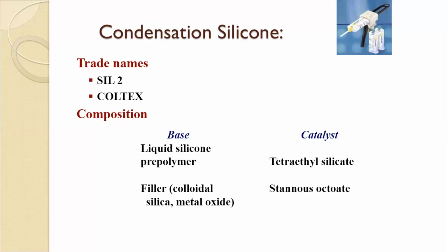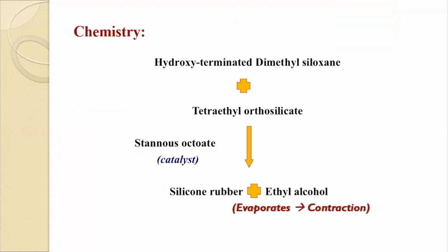Your base paste would consist of alpha hydroxy terminated polydimethyl siloxane. The curing of this material involves a reaction of tri and tetra functional alkyl silicates in the presence of stannous octoate as a catalyst. The material sets by cross-linking between the terminal groups of the silicone polymers and the alkyl silicates to form a three-dimensional network. Here, like in the last one, water was released. Here, ethyl alcohol is released as a byproduct.